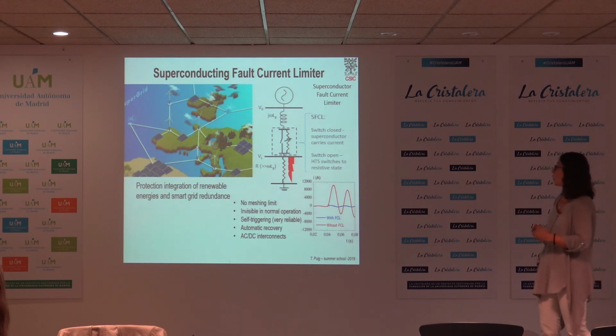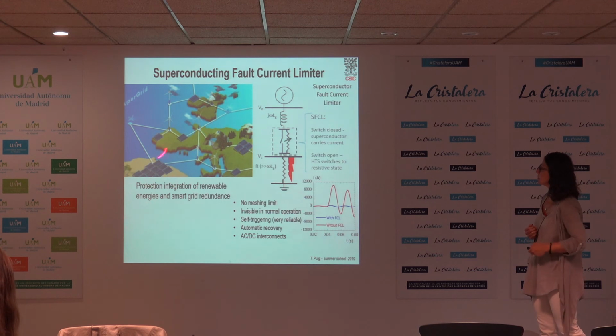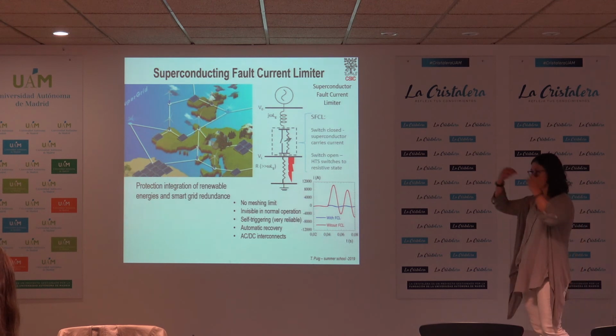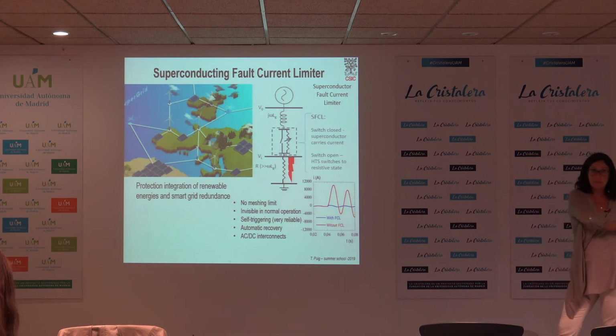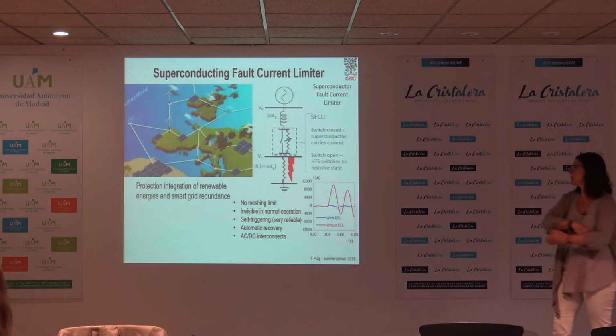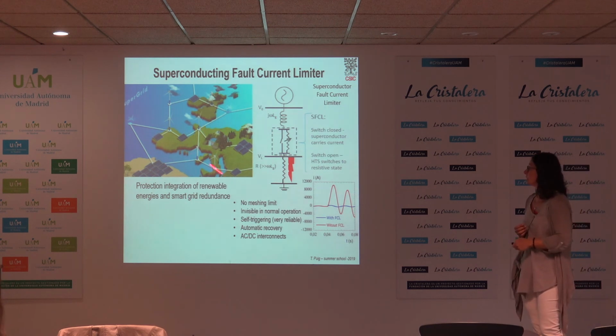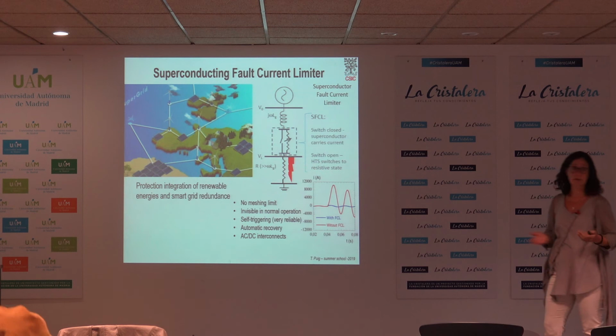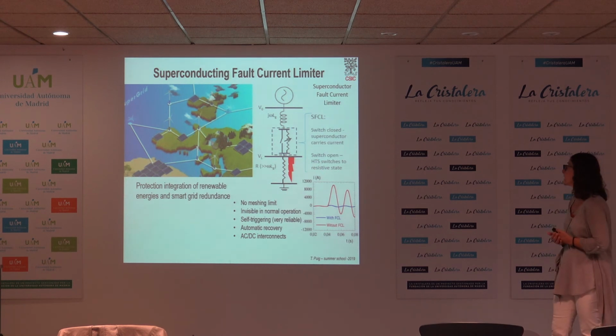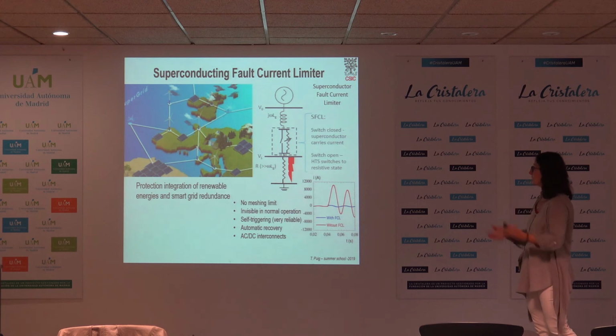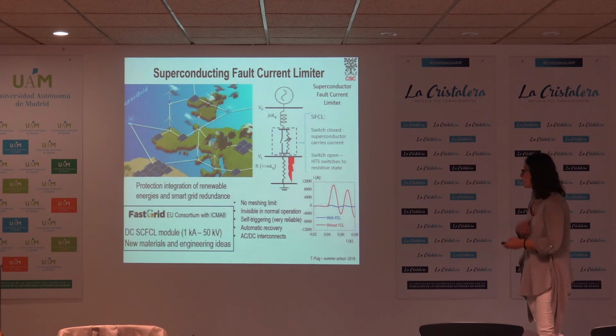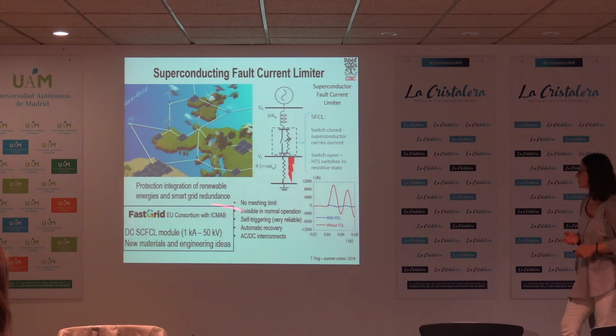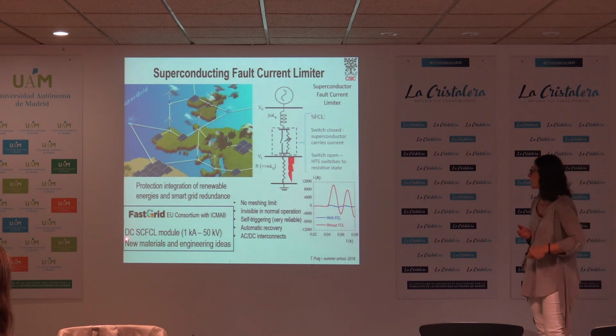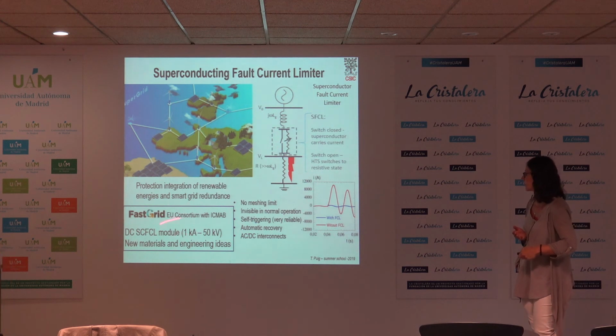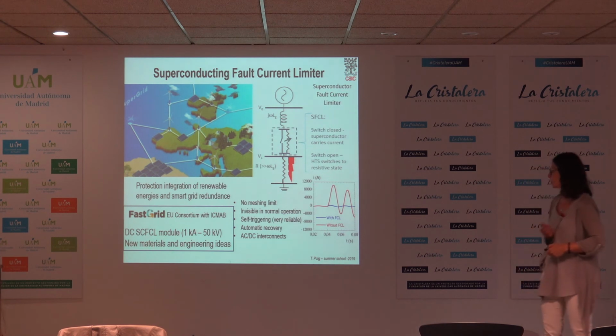It is also interesting now that the possibility is being considered of having generation of energy in one place and distribution in another place. So you need very long distances that have to work with DC cables, which is better because less energy is lost than with AC cables, but they also have to be protected with fault current limiters. And here, for example, we are now in a consortium in the EU called FastGrid, which is able to demonstrate that we can make one cable, also acting as a fault current limiter, of 1 kiloamp at 50 kilovolts.